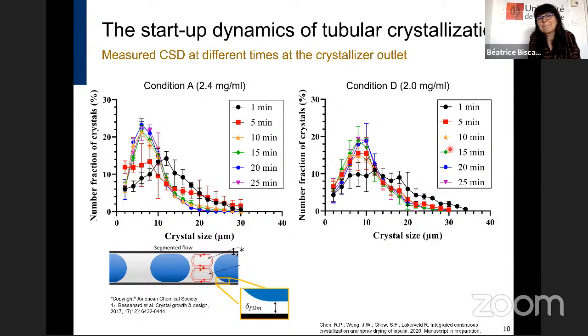That's a very good question. Actually, yes, insulin is quite expensive, so for each run we normally operate for one round. For the integrated process, we operate for 1 hour, and for standalone crystallization, we operate for half an hour. And the initial concentration is around 2.4 milligram per milliliter. So for each experiment, it can cost, I think, around hundreds of Hong Kong dollars. So it's quite expensive. But the productivity of this process is not very high because we are using a tubing that has a very small inner diameter. So the mass of insulin that we can produce per hour is actually limited.